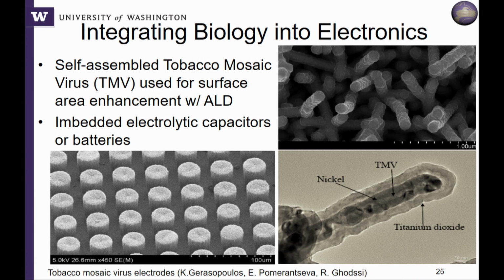And so we can self-assemble these little viruses, and you can see here these are collecting on the surface here, and they have a nice long cigar-shaped kind of structure to them. And if we take our traditional fabrication techniques, we can make a bunch of pillars and then functionalize those and then get those viruses on there, so we can get these huge surface area enhancements.